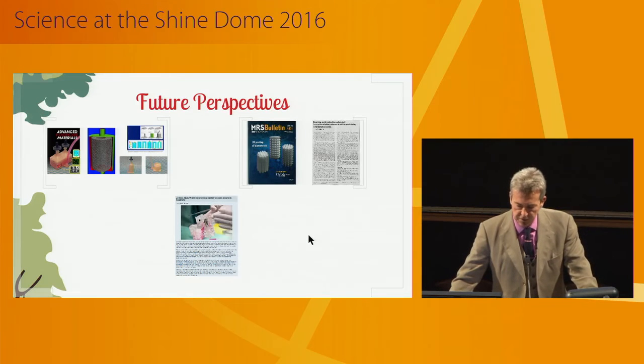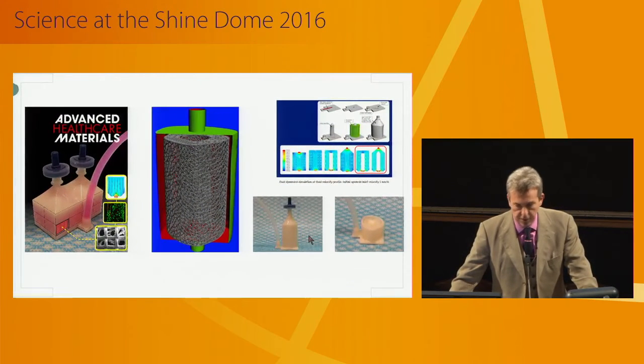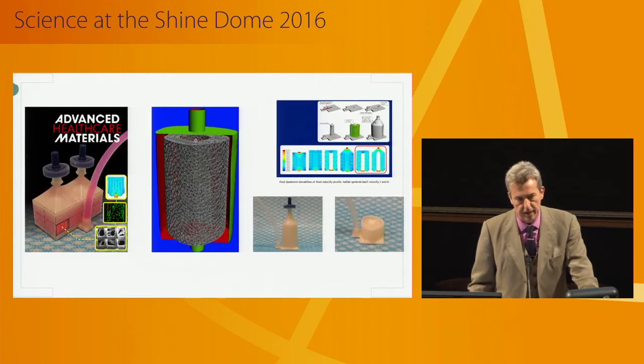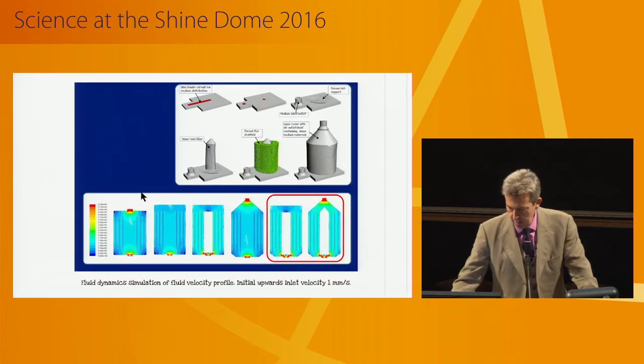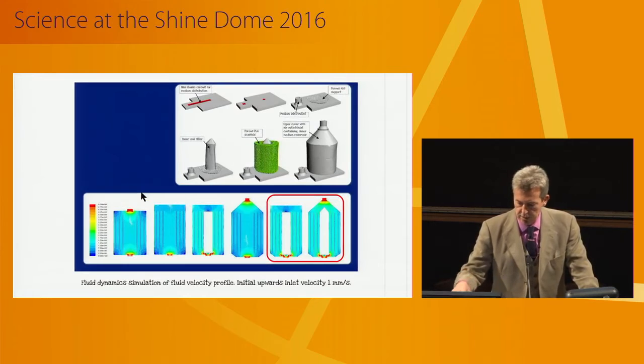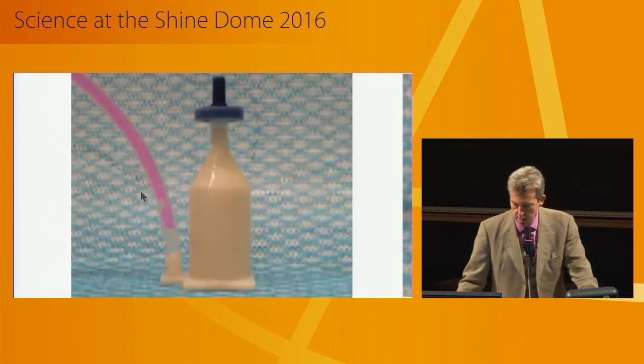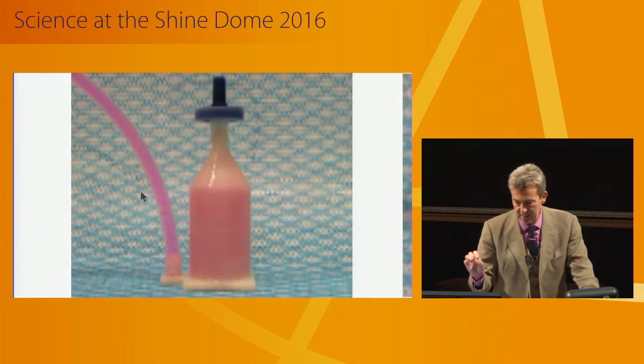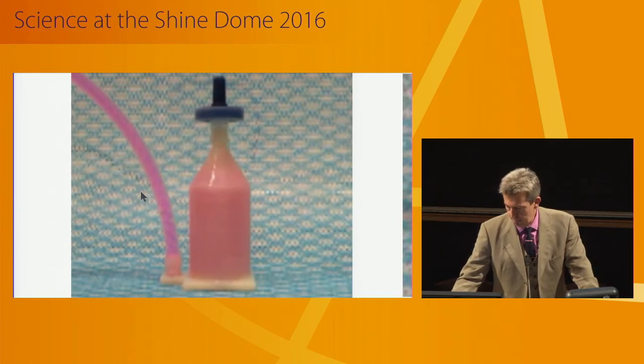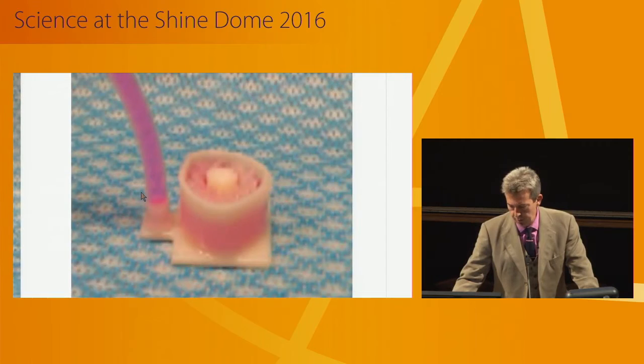Another direction where we see 3D printing going is that we can now print a scaffold that is patient-specific, and if we want to use cells, then we build the bioreactor directly around this process. That again allows us to customize the process. Again, the science is very important. Here you see finite element modeling, where we are looking at the mechanical properties as well as the flow properties through such a scaffold. And here you see how it works. The scaffold is inside a closed system, and we are pumping the media in and out in an incubator. If you cut the system open, you see a very nice flow profile of the cell culture media.